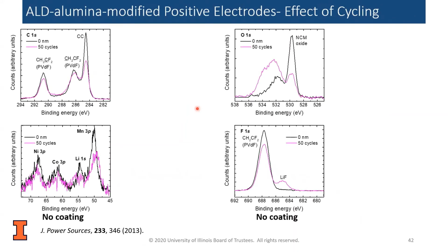So looking at the XPS, these are comparison of 0 and 50 cycles, so 0 nanometer before and after 50 cycles. We can see that we're getting coating and increase in the carbon signal, so the carbonate signal from the oxygen. And we also notice that we're getting a little bit of diminishment of the manganese. So eventually after 50 cycles, we are starting to lose some manganese.